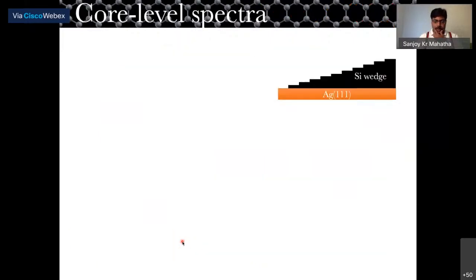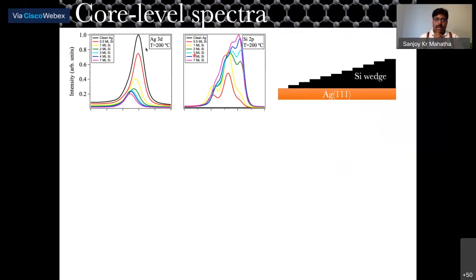Then we decided to do this experiment. We grew a wedge, basically multi-layer silicene with a wedge structure on silver 111 at a particular temperature. Then we acquired photoemission from the silver 3d core level and silicon 2p core level as a function of thickness at different points. You can see these are changing slowly: as we put more and more silicon, the intensity of silver drops, the intensity of silicon goes up, and the shape is also changing.